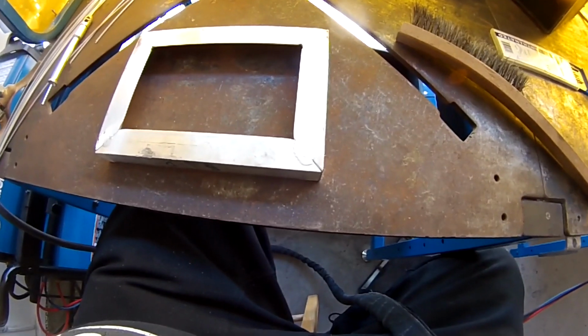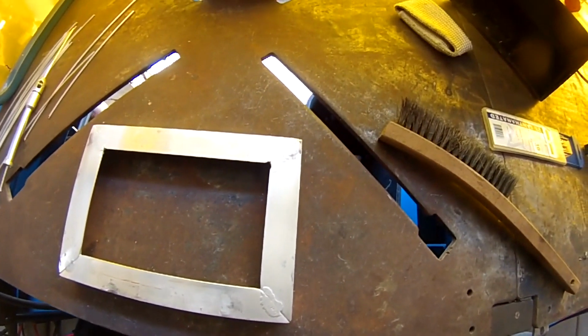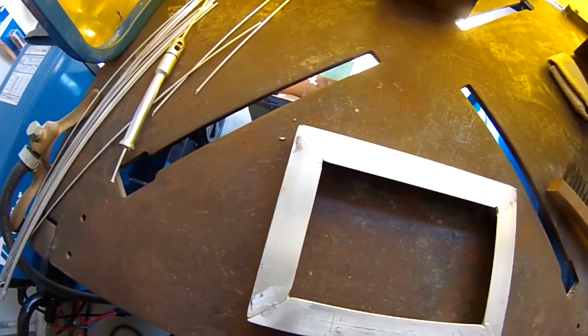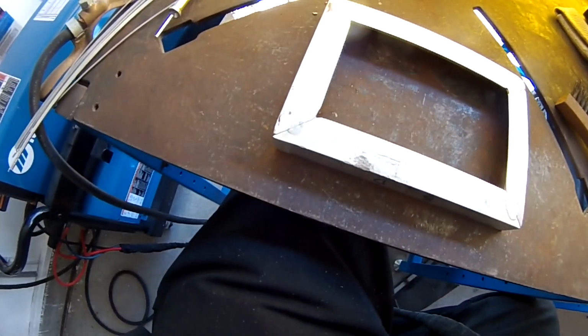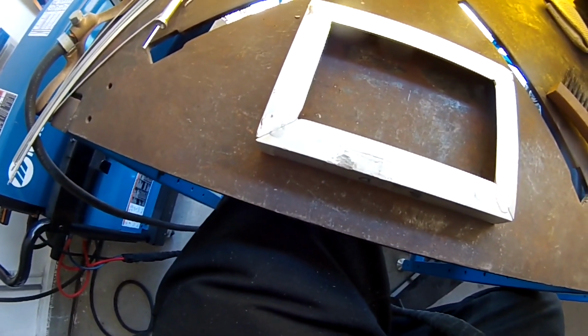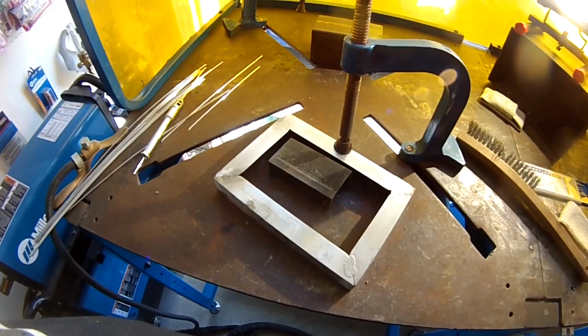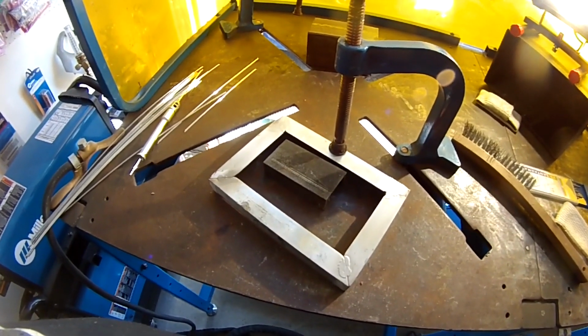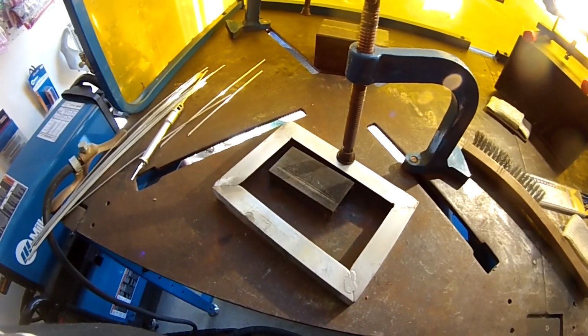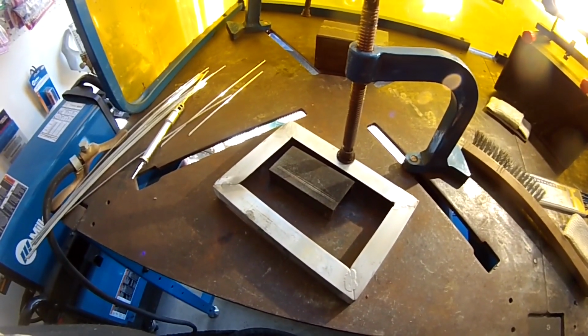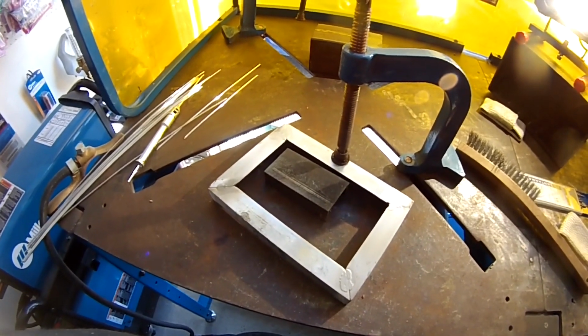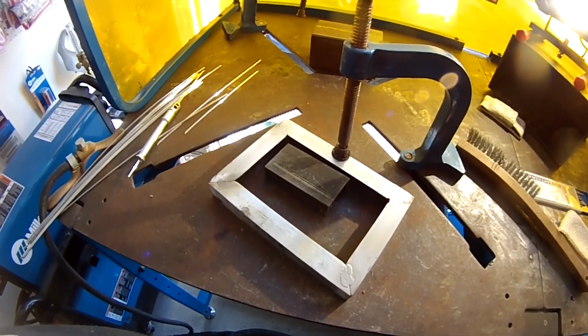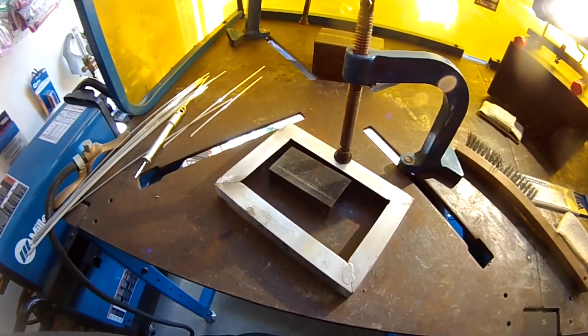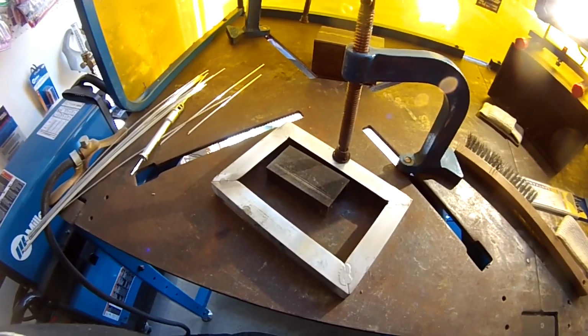Here's the penetration that I got on the other side. Did not penetrate through all the way, so I'm going to weld up that side. I'm going to put that channel under there. That channel is made of steel, and the reason I'm putting it under there is so the bottom doesn't fall out of the aluminum. You know how when you're welding aluminum and the whole thing just drops out from you? If I put the steel down there, that won't happen.